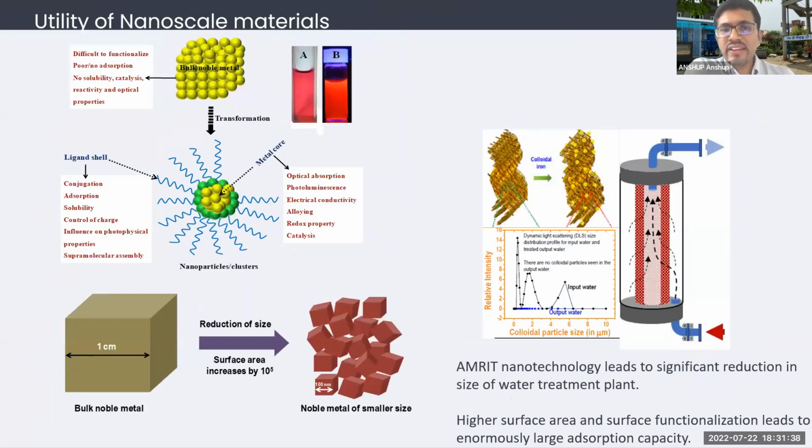Nanoscale materials are essentially the materials which we make from a bottom-up approach. We start with ions, or ionic level species, and then depending on whether we are looking for metal oxide or metal nanoparticle, we take them to nanoscale size, and they are deeply embedded inside a matrix so that they do not undergo further transformation to micron size particles.